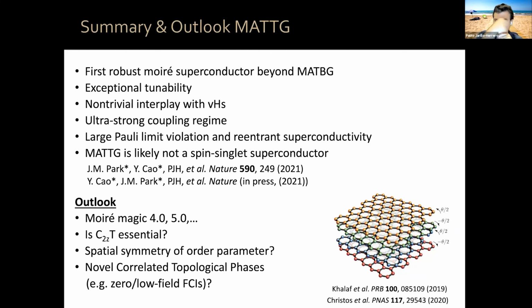I thought you were going to ask a question directly about the previous stuff. So let me just make a further comment. So indeed, the twist angle in these devices is not exactly identical across the entire device. Different devices have different degrees of twist angle disorder, we call it, or twist angle inhomogeneities. The important thing is that in general, what we see is that for a device to exhibit magic angle graphene characteristics, meaning superconductivity, correlated insulator states, etc., the twist angle disorder has to be smaller than a certain amount. So roughly, since we know that this physics appears at about 1.1 plus or minus 0.2 or 0.3 degrees, when you characterize locally the disorder by a Gaussian in twist angle over your device, that Gaussian has to have a width of less than 0.1 or 0.2 degrees in order for it to exhibit these characteristics.